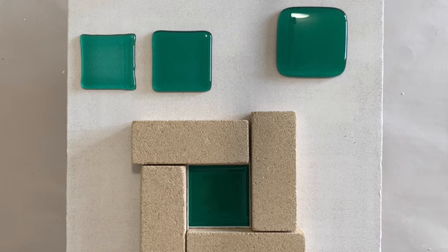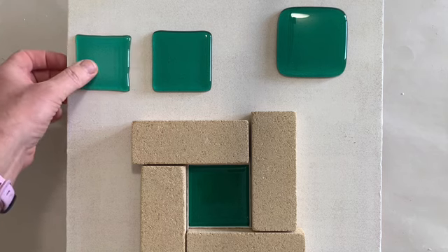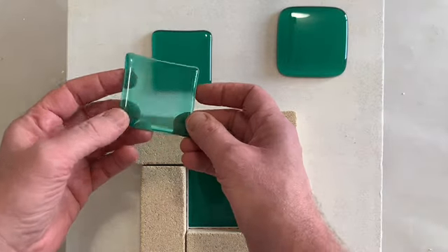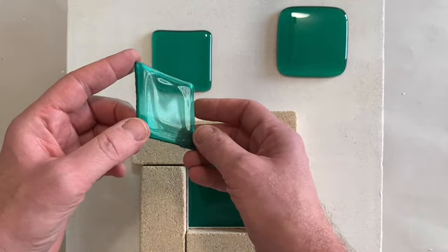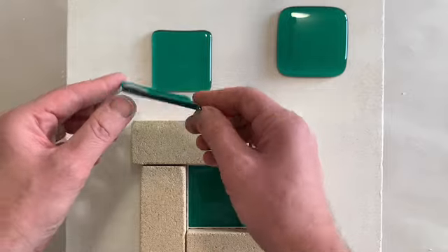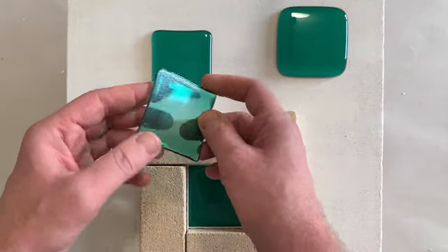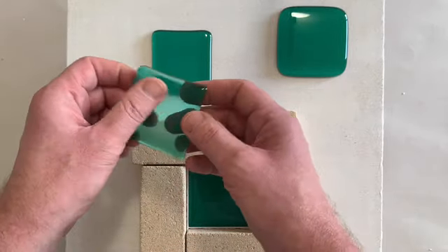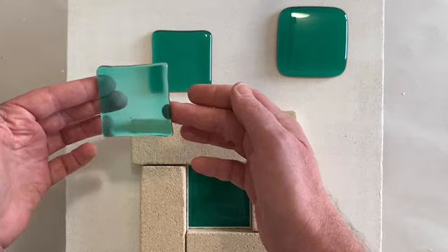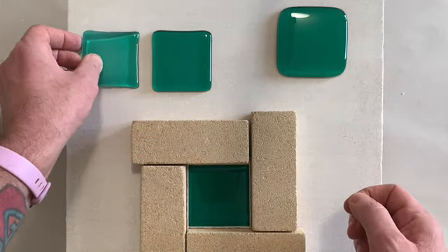The samples on this kiln shelf were fired at 1460 degrees Fahrenheit and held for 10 minutes. The first sample is one layer of glass, or 3 millimeters thick. The deformation you see is referred to as dog boning and will occur every time a single piece of glass is fired to a full fuse temperature.